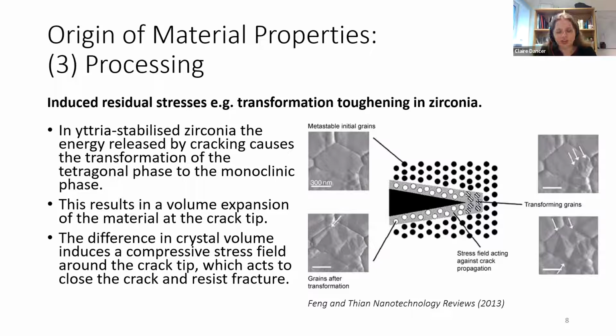So zirconia at room temperature in its stable crystallographic form is monoclinic. At high temperatures, it's tetragonal. And what was found was if you add a small amount of yttrium oxide to the zirconium oxide, you can stabilize that tetragonal phase at room temperature. Not everywhere in the material, but in enough of the material that you get a degree of that tetragonal phase in the structure. And what was observed in the 90s, this is not the original paper, just a nice diagram to show you what's going on, is that if you then had a crack in that material, perhaps you put in a deliberate crack with a hardness indenter, and you allowed that crack to move through, there was a change that happened at that crack tip.